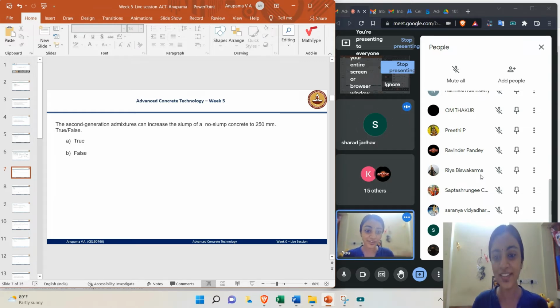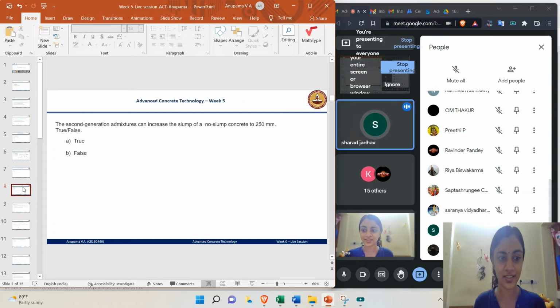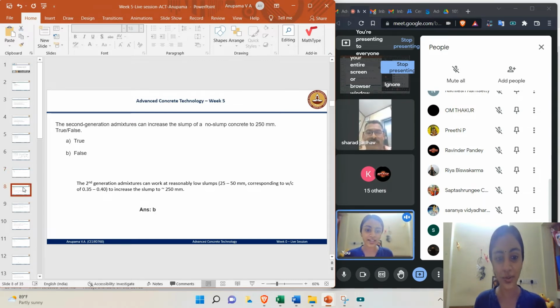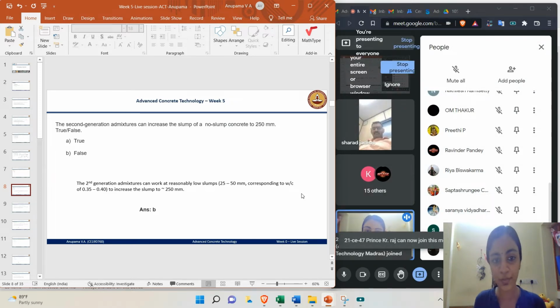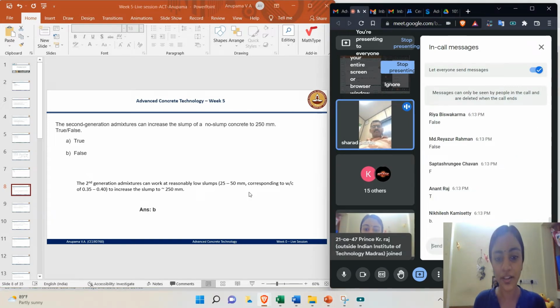If all of you, not just Sharad, please reply in the chat box and be interactive so that we can have an interesting session. So the correct answer, as rightly told, was B. The second generation admixtures can work at reasonably low slumps. It cannot work at a no slump concrete. It can work at a reasonably low slump, that is 25 to 50 mm, corresponding to a water cement ratio of 0.35 to 0.4, and it can increase it up to 250 mm. That is true, but not from a zero slump concrete. It can increase, but only from 25 to 50 mm.